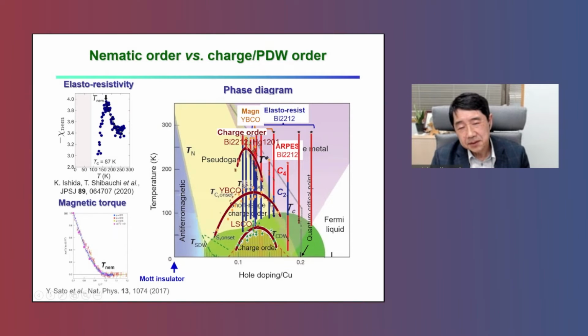So this blue part, broken symmetry part, is within the pseudogap phase, or even coincides with the pseudogap phase boundary. So this looks like nematicity is closely related to the pseudogap opening, and includes the charge order or PDW state.